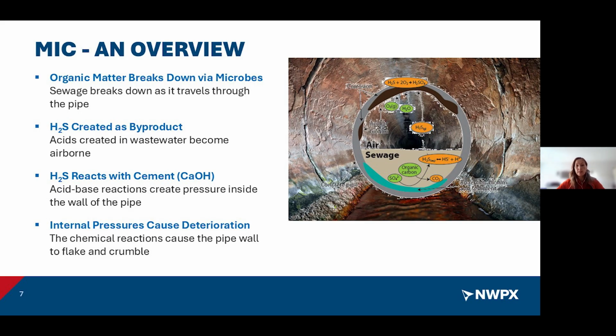And once it settles down, it reacts with bacteria on concrete and oxidizes into sulfuric acid, and then sulfuric acid reacts with cementitious materials in concrete, and it creates gypsum. And gypsum in moist environments swells and starts crumbling. So that's a very simplified version of how concrete deteriorates under H2S gas environments. There are biofilms created, gypsum forms, and concrete gradually starts crumbling, and you have a loss of thickness of the wall, and then it eventually can get to your reinforcing steel.